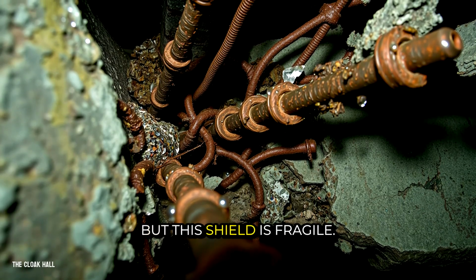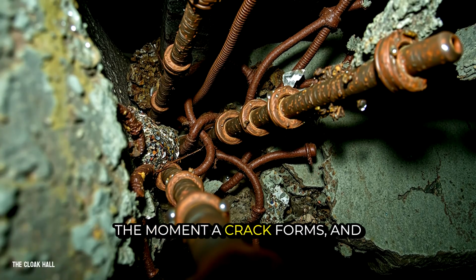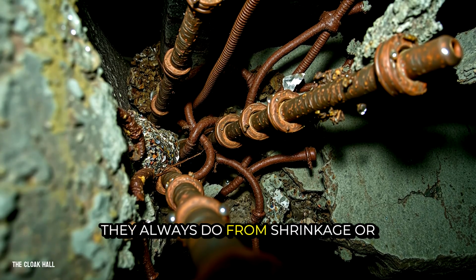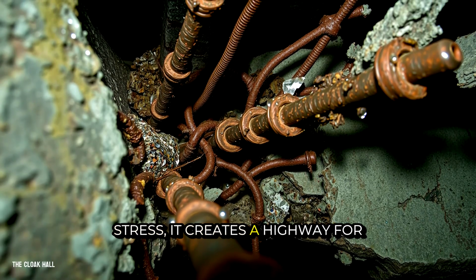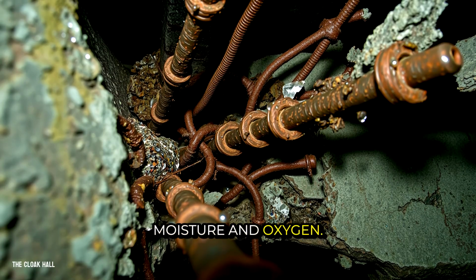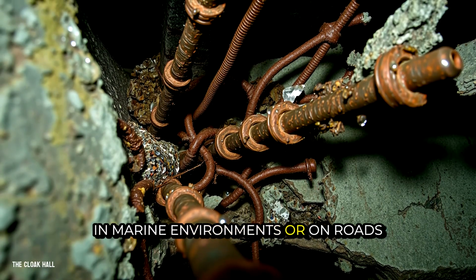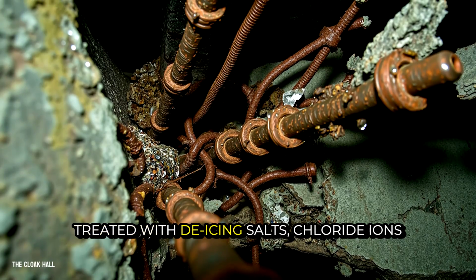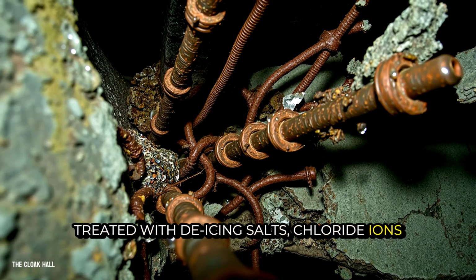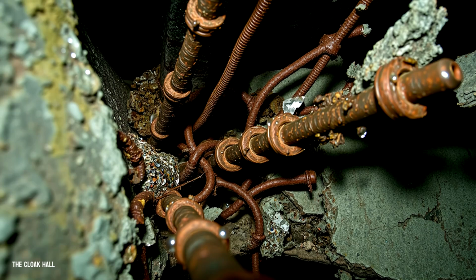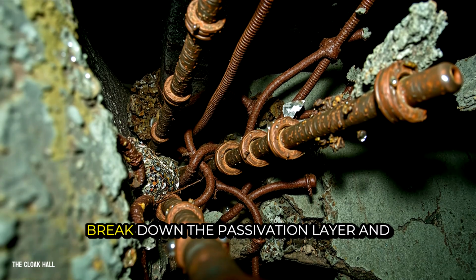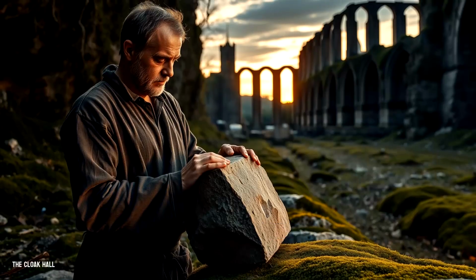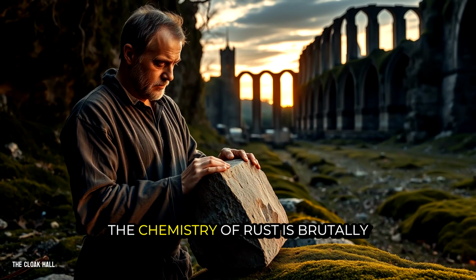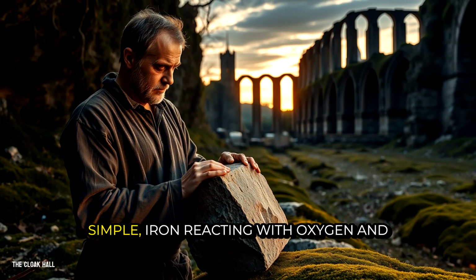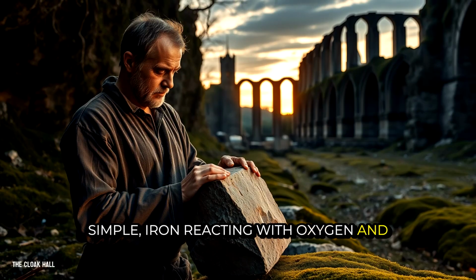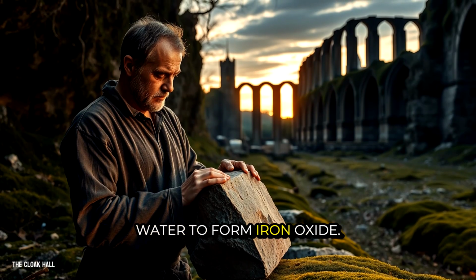But this shield is fragile. The moment a crack forms, and they always do from shrinkage or stress, it creates a highway for moisture and oxygen. In marine environments or on roads treated with de-icing salts, chloride ions hitch a ride on that moisture. When they reach the steel, they break down the passivation layer and corrosion begins. The chemistry of rust is brutally simple, iron reacting with oxygen and water to form iron oxide.